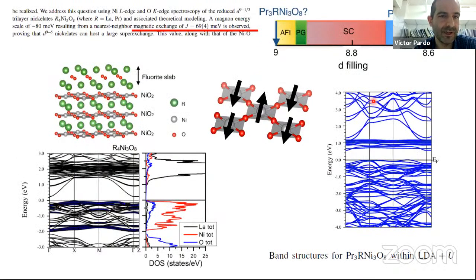Yeah, certainly. In the 438, for example, in the higher order nickelates, you would have this naturally, because in this case you have three layers of nickel O2, but they are separated by this fluorite slab that blocks the nickel-nickel off-plane hopping. So if you block the nickel-nickel off-plane hopping, what happens is that, again, you look at the band structure and the nickel d z-squared bands are contained. Let's say they are not highly dispersive, and you don't have that metallicity in the parent compound.